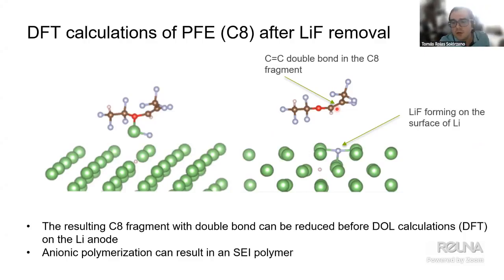One, that there is forming of lithium fluoride on the surface of the lithium, which is a typical species that can be formed in the SEI of a battery, of a lithium sulfur battery especially. And the carbon-carbon double bond compound gives us a hint that could be the initial stages of the formation of a polymer, which also could be a favorable species to be formed on the SEI.